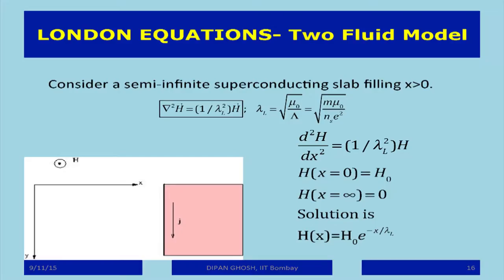Now in that case, because the material is semi-infinite, the only variation that can happen has to happen in the x direction, because in the y direction and z direction, there is no variation possible. So therefore, my del square H can essentially be written as d square H by dx square, because that's the only direction in which H can vary. So this equation becomes d square H by dx square equal to 1 over lambda square H. The solution of this equation is very simple, H of x equal to H0 e to the power minus x by lambda. So in other words, if the field at x equal to 0 is H0, then the magnetic field strength, as you go through a distance of lambda, which has been calculated earlier, becomes 1 over e of its value.